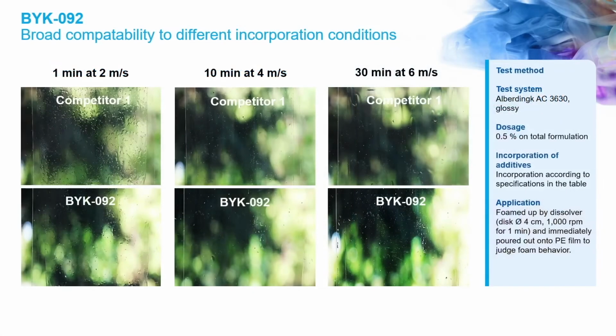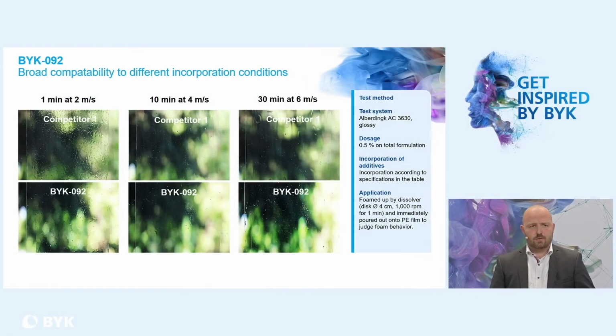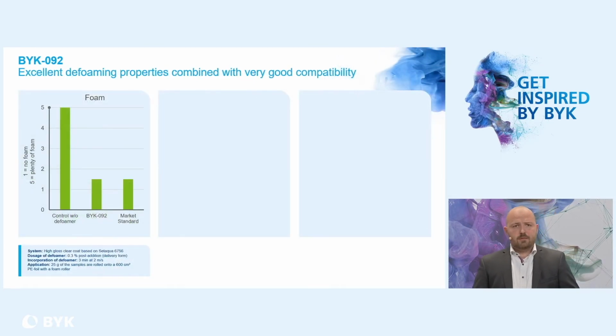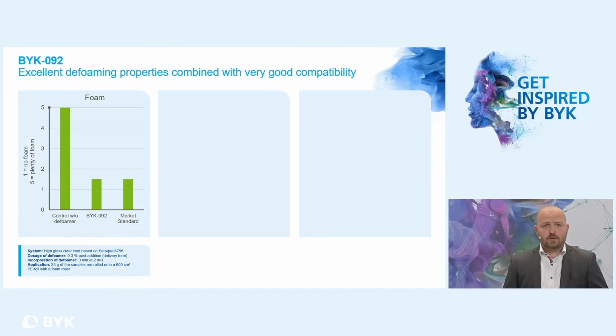When you use very harsh conditions for the incorporation, you can over-emulsify your defoamers, so they lose efficiency again. At 30 minutes, at 6 meters per second, for example, the BYK 092 still gives you good results and a nice surface, while you see the first surface defects again in the competitor product. So you have a very broad compatibility with different incorporation methods when you use the BYK 092, which is clearly another advantage.